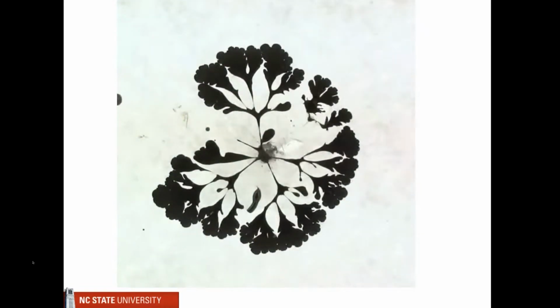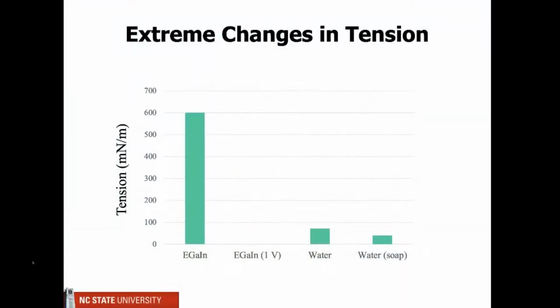Now, if you didn't quite appreciate this, let me say it in one more way. This is a bar chart of the surface tension of these fluids. So here's poor little water, only 70. Remember that number 70? And if you want to lower the surface tension of water, you can put soap in it. So it goes down to about 30. And we feel pretty good about that. That's the basis for shampoo and washing our hands, and that's good, 70 to 30. Well, here's liquid metal, and it's like 600, 700, depends on the environment.